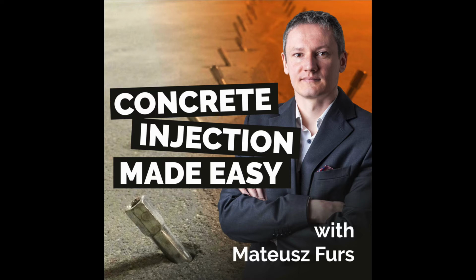I like to say that since EP has a higher viscosity, resembles honey, not water, and has a lower bonding ability to wet concrete than to dry surfaces, to me, all this makes EP harder to apply than PU and potentially not as effective. So when water is present in the crack, and I know that the structure will not collapse, which is the case in most situations I have ever seen, I easily choose PU resin, run my injection, and I know that the structure is watertight and safe.